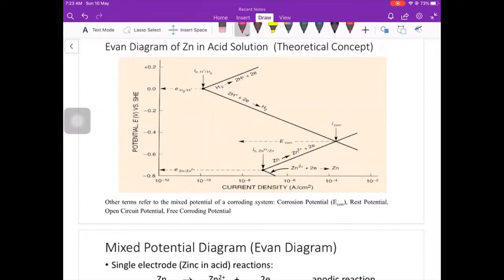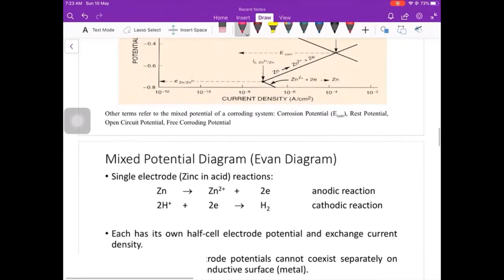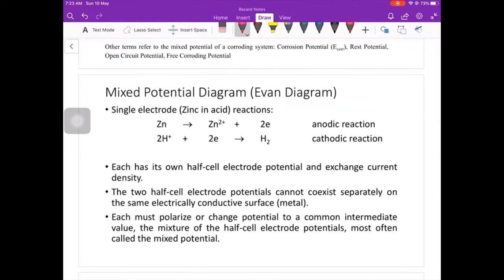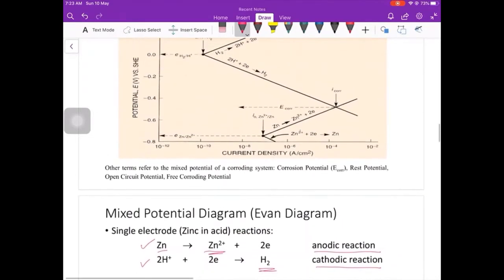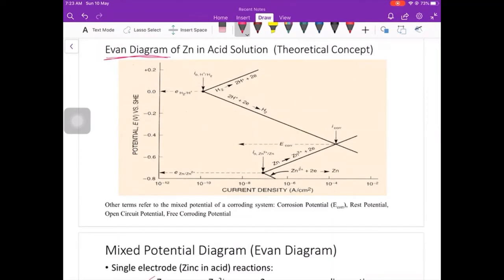Okay, this is an example. Look at this. When you immerse zinc in acid solution, theoretically it will form this diagram. We call it Evans diagram or mixed potential diagram. Look at this process. This is the anodic zinc. This is the environment, cathodic. So zinc is immersed in acid. What will form at this cathodic reaction is hydrogen evolution, and the anodic reaction is zinc dissolving to zinc 2 plus.